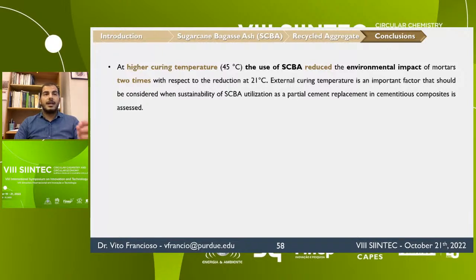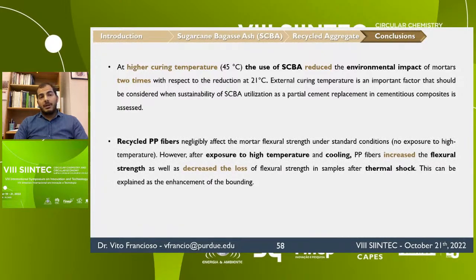As we have seen, at higher temperature, at 45 degrees Celsius, the use of sugarcane bagasse ash reduced the environmental impact of mortars 2 times more with respect to the reduction at standard curing temperature. Also, the recycled polypropylene fibers, even though they have a negligible effect on the mortar flexural strength under standard conditions, so no exposure to high temperature, after exposure to high temperature and cooling, the polypropylene fibers increase the flexural strength as well as decrease the loss of flexural strength in samples after thermal shock. And this can be explained by the enhancement of the bond.